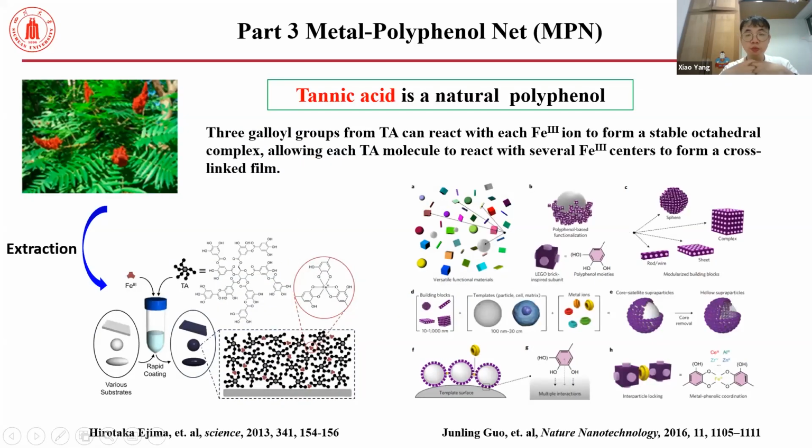Tannic acid is a natural polyphenol, and this group is published by Frank Caruso. They use the tannic acid to react with the iron, and it can form a stable complex on any universal surface.